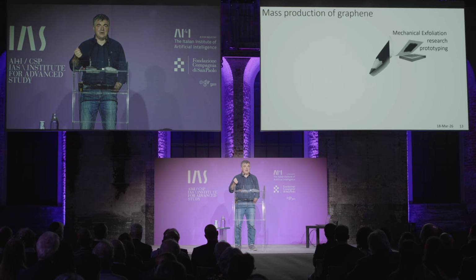When you rub your graphitic pencil against paper, you basically shed those flakes from the layered material graphite. And we simply used Scotch tape to split it. Every time you put Scotch tape on two sides and split it, you make it twice thinner, and if you do it many times, you basically get to exactly a single layer. To our shame, we still use the same method, and pretty much every single research lab uses this method up to now.